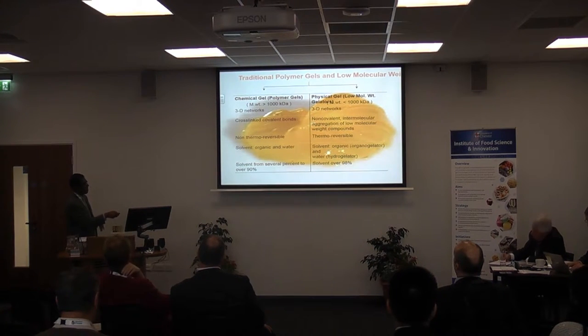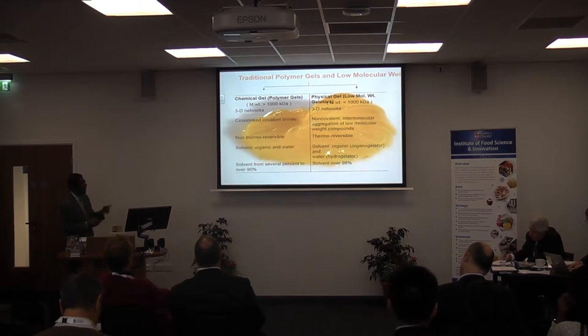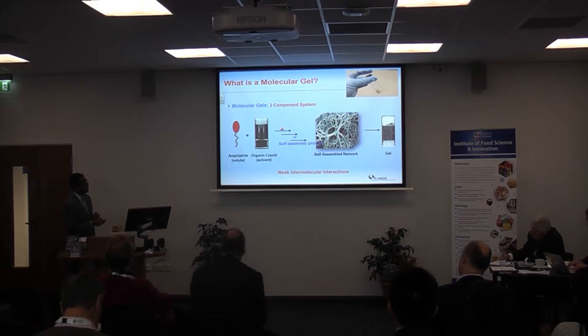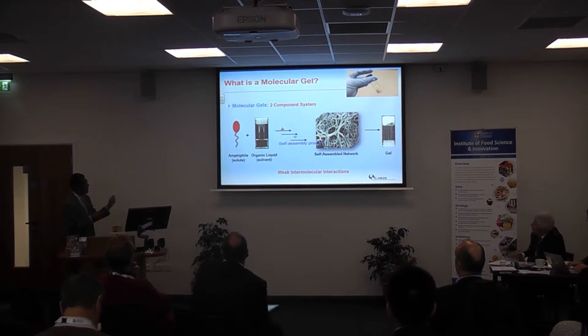In both cases, whether it is polymeric gel or small molecule gels, we can encapsulate almost 90 to 98% of the solvent in the gel systems. And what we do in our laboratories, we are designing, synthesizing, and creating molecules with a hydrophilic part and a hydrophobic tail, lipid molecules. And not all lipid molecules create gel. Few lipid molecules create gels.